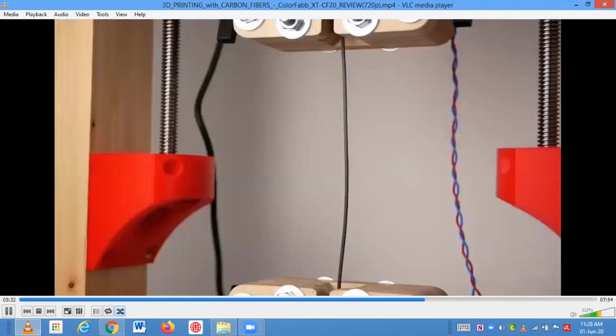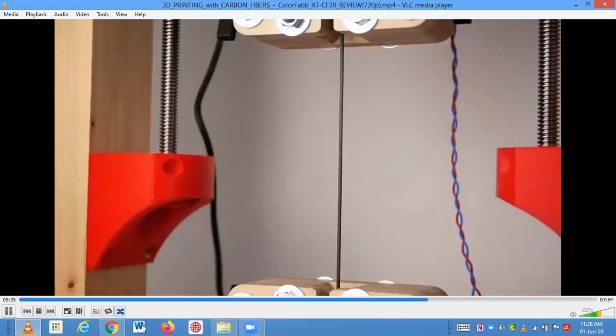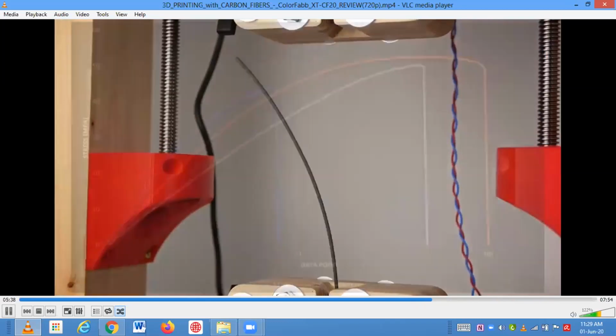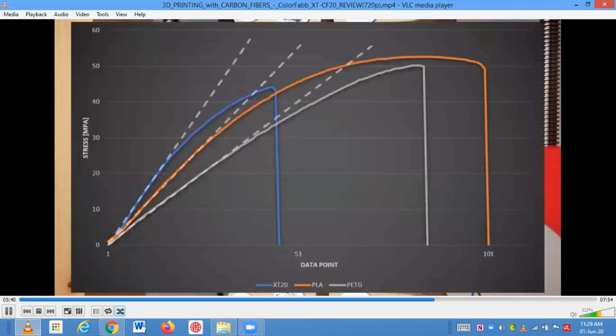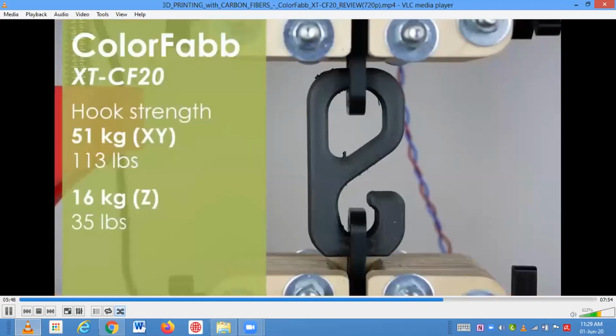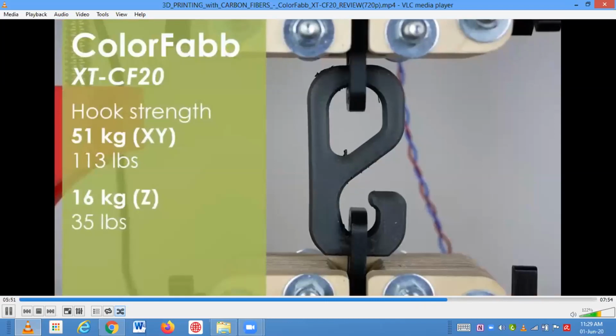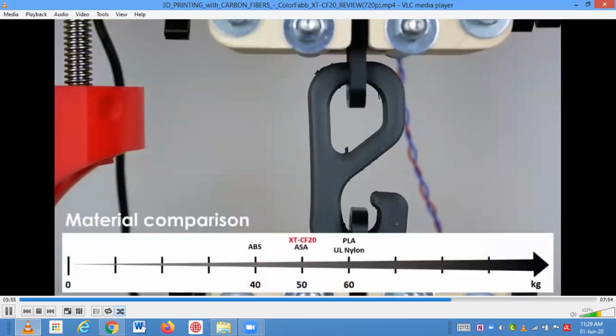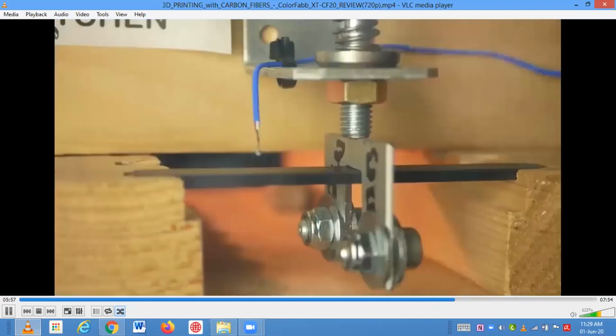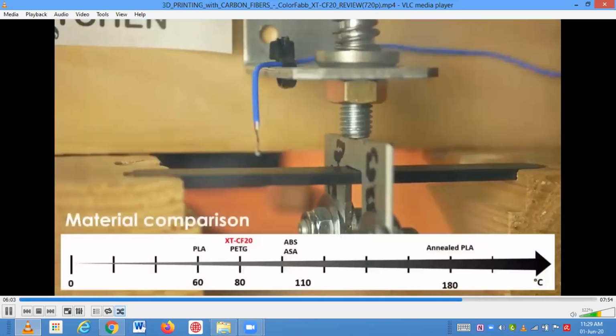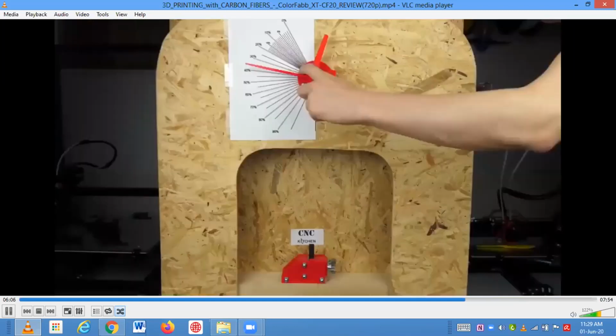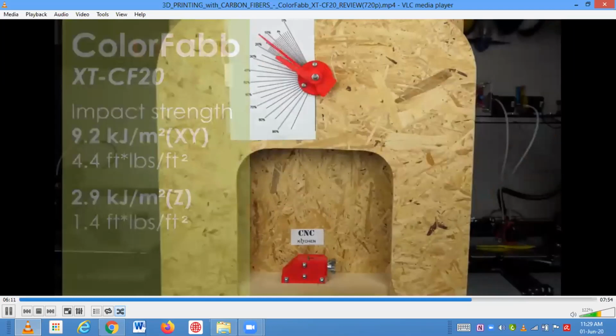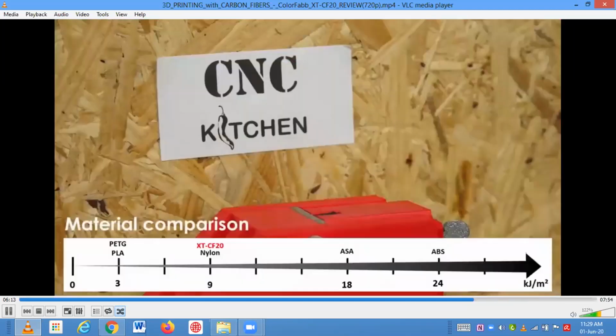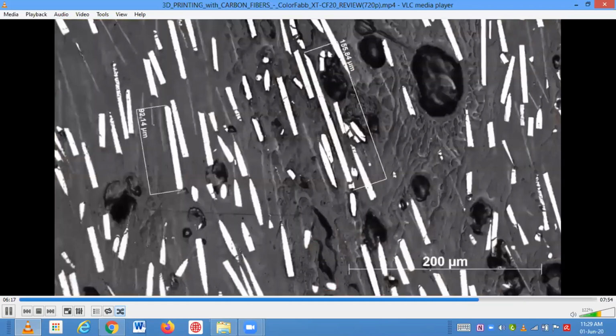The filament test also confirmed the superior stiffness of this material, even in comparison to PLA. The slope at the beginning of the test indicates the modulus. The steeper it is, the more rigid a material is. My test hooks failed at around 50 kilograms of load, which is in the mid-range. The standing one was only able to bear 16 kilograms until failure, which confirms the previous tests. Temperature resistance was good and the material stayed rigid up to 80 degrees Celsius and then totally failed at 85 degrees Celsius. The impact strength was okay and an improvement over regular PETG or PLA, but far away from the toughness of, for example, polycarbonate.